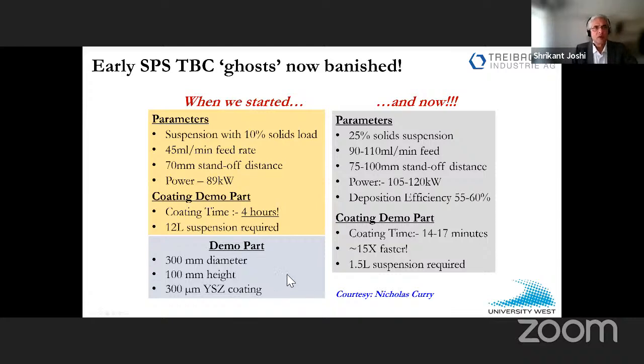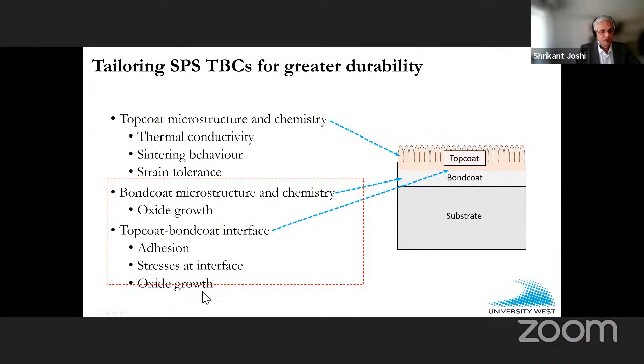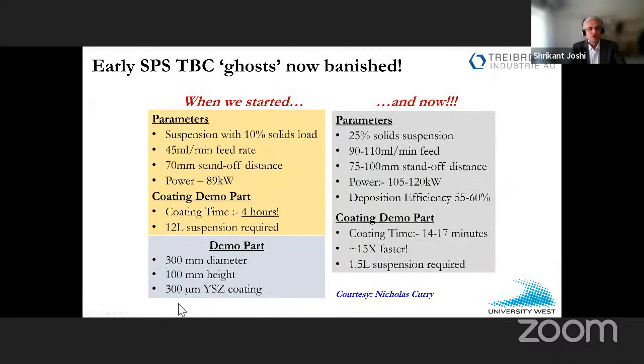Some real numbers from our own work. Before my time, honestly. This was done way before my time, but this data from our lab here in Sweden. So when we started doing these TBCs using suspension yttria stabilized zirconia, the typical solid loading was about 10%. All other numbers here, but to coat a 300 diameter test specimen, 100 height, with 300 microns would take us about 4 hours. It would consume about 12 liters of suspension, right?